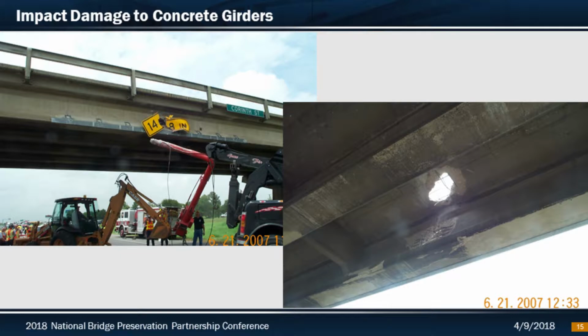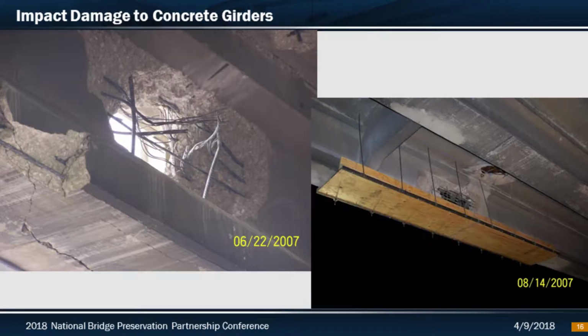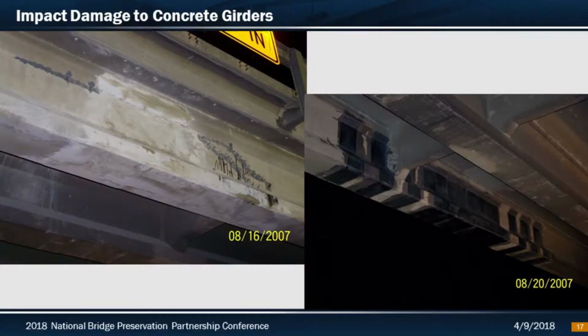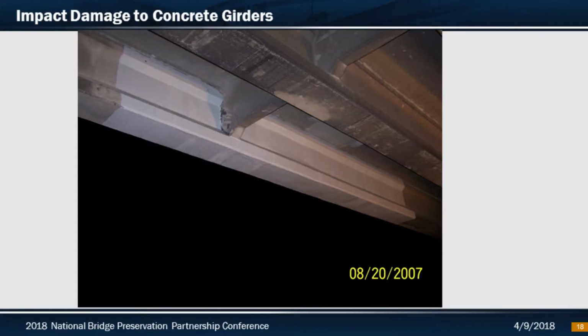Here's damage in Dallas in '07, another one over the interstate. This one was pretty much a complete punch through on the beam web and also the deck. Several prestressed strands were severed with the hole going all the way through the web. The bottom flange was ruptured, so we went back in and retensioned. You can see on the right the retensioning with some of the cable splices, and we did the beam repair. We then came in and did a crack injection on the remainder of the cracks. You can see on the right the longitudinal wrap on the bottom flange as well as the U-wraps, and then additional U-wraps on the cracked section of the girder. Top coat applied. This one was done in a couple of months, which again is saving a lot of time and a lot of money, and disruption to traffic.